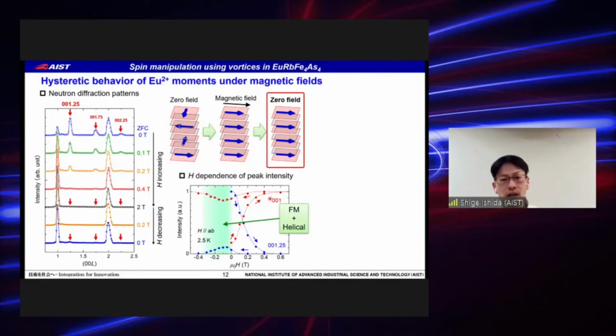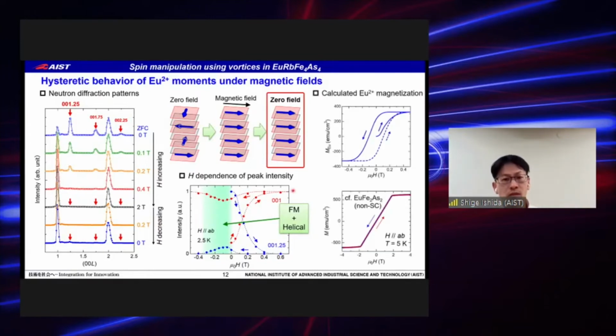Based on these results, the magnetization coming from the europium moment can be calculated, showing clear hysteresis. Note that the magnetization of Eu-122, the non-superconducting counterpart, shows negligibly small hysteresis. Therefore it is expected that the interaction between the europium moment and vortices is the origin of this hysteretic behavior.